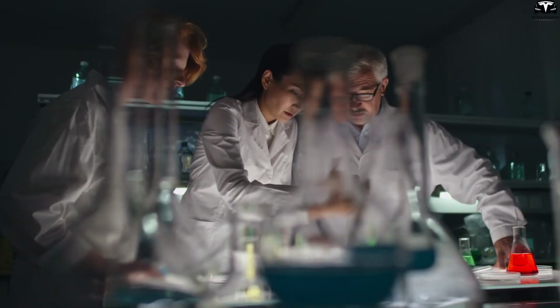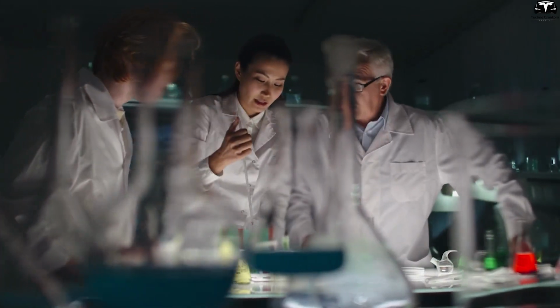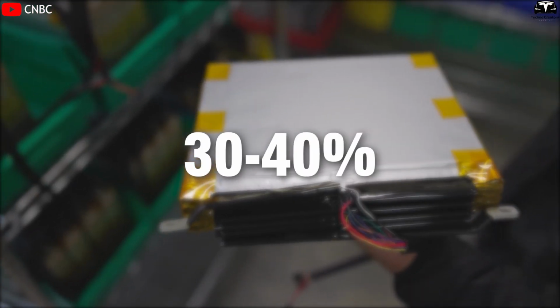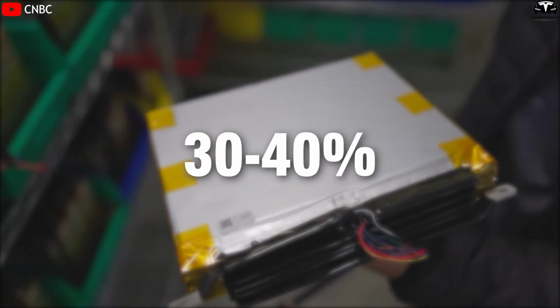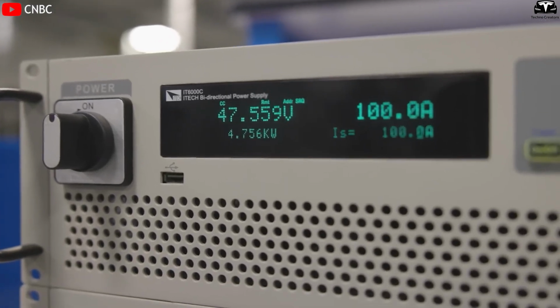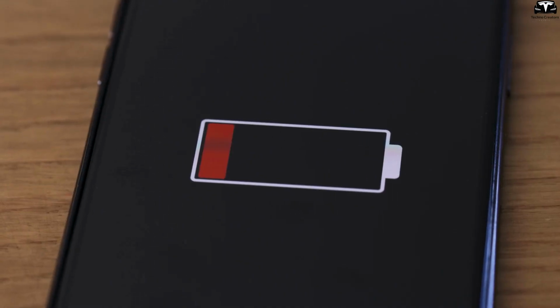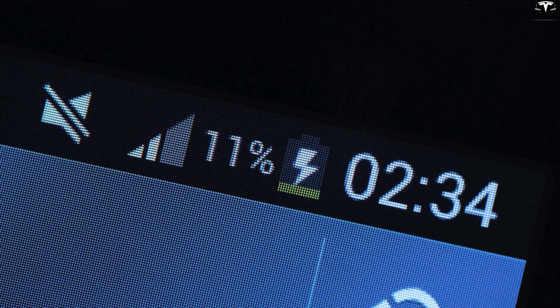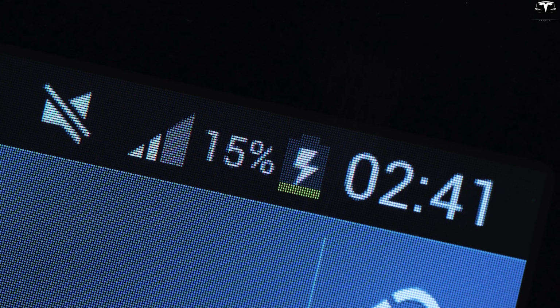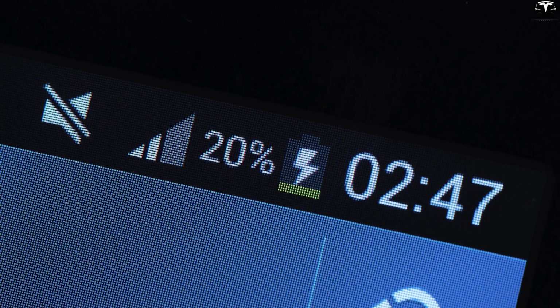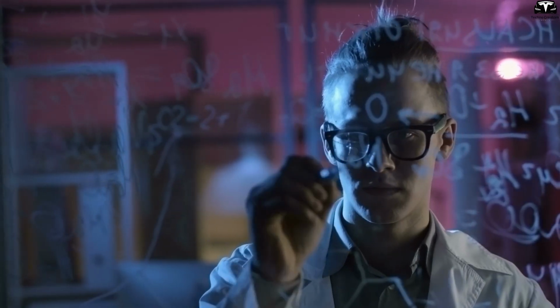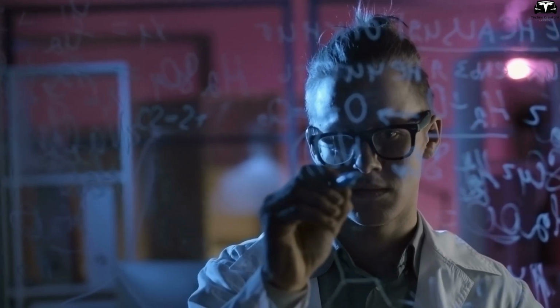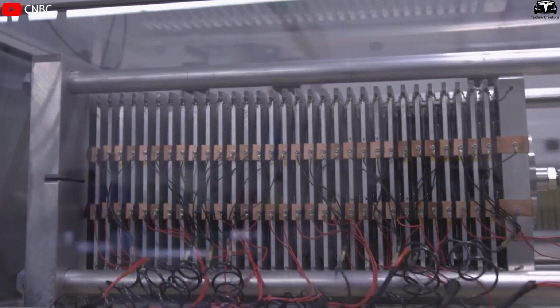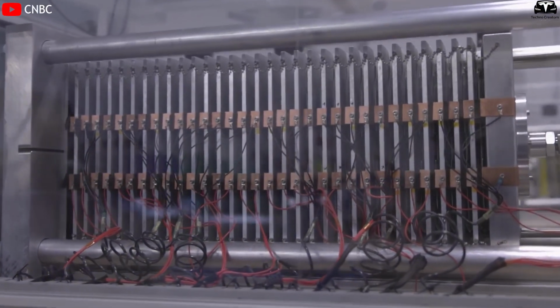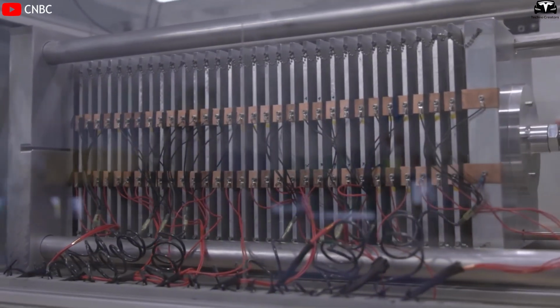Recent studies have shown that organic batteries with aqueous electrolytes lose up to 30 to 40% of their voltage after just a few hours when left at open circuit. This makes devices using such batteries unstable, unable to store charge for long periods, and very difficult to commercialize. This is also why most previous studies, despite achieving good capacity, either do not publish or deliberately ignore the self-discharge rate, a serious but rarely mentioned problem.